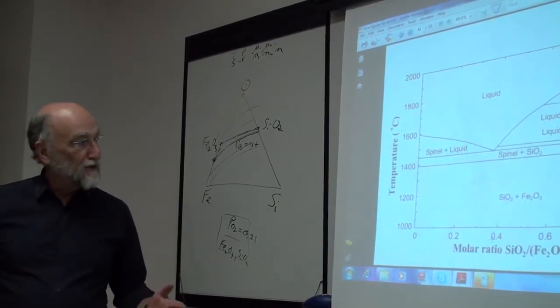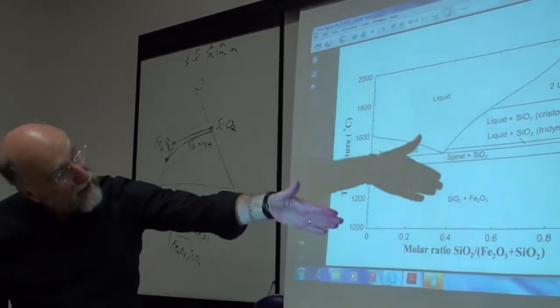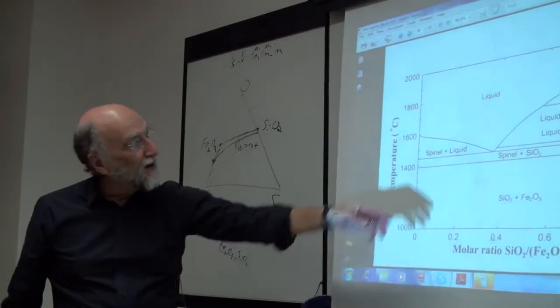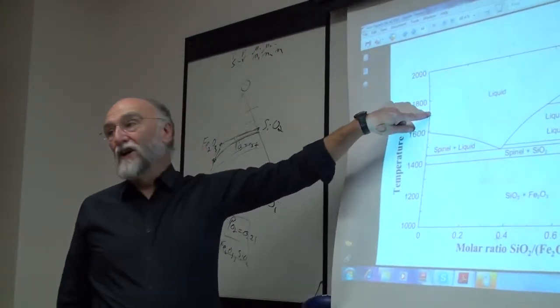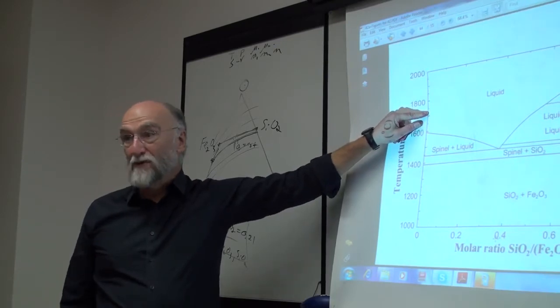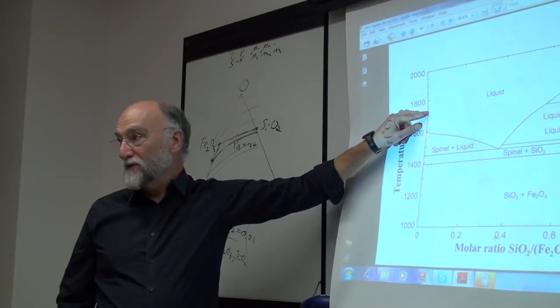Okay, so this is the misinterpretation. You say over here you've got pure Fe2O3, this is the Fe2O3 SiO2 diagram in air, so this point here is clearly pure liquid Fe2O3. It's not. This is the liquid at whatever the liquid composition happens to be, a mixture of FeO and Fe2O3 at 0.21 atmospheres.